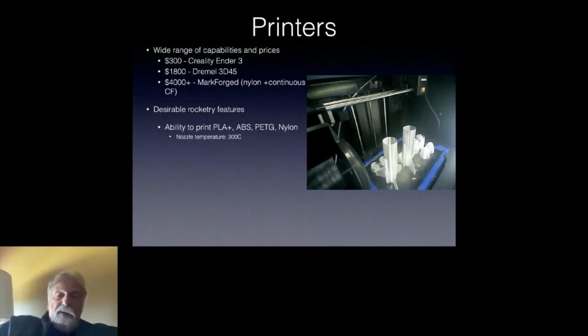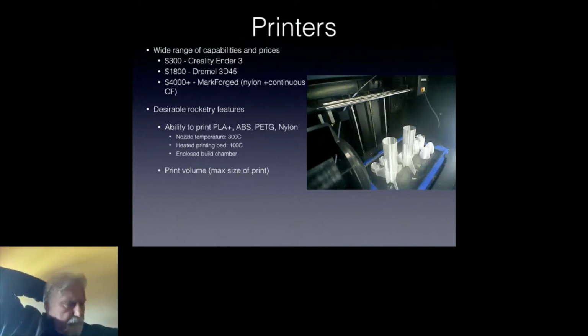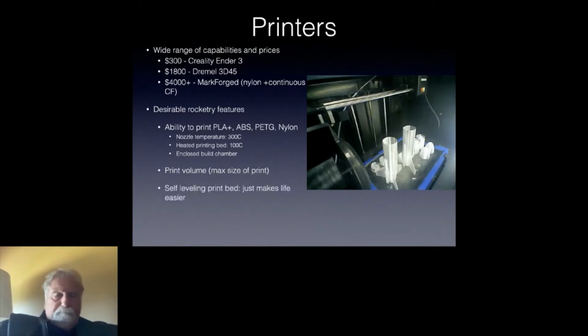I would look for a maximum nozzle temperature of about 300 degrees C. I think a heated printing bed is really valuable, up to about 100 degrees C. And an enclosed build chamber really reduces the noise and helps keep a more even temperature as you are printing, which helps bonding between layers. The key thing is the print volume. The maximum I've been able to print in my printer is 150 millimeter nose cones, sliced vertically, because the length of the nose cone is longer than the build height.